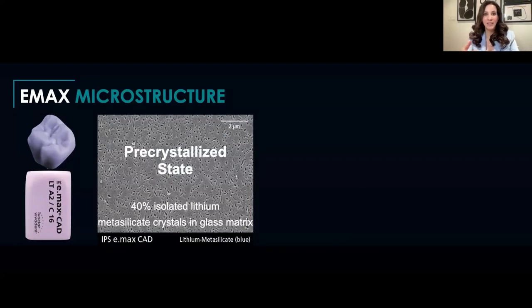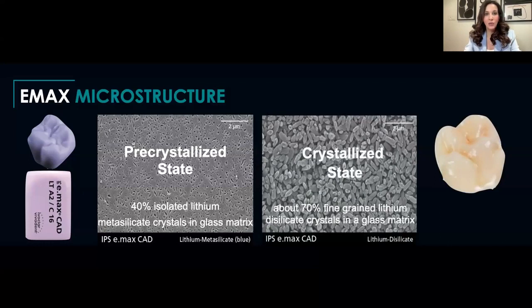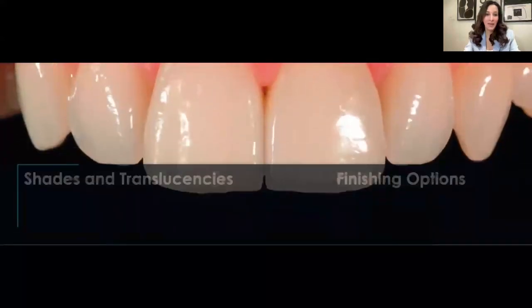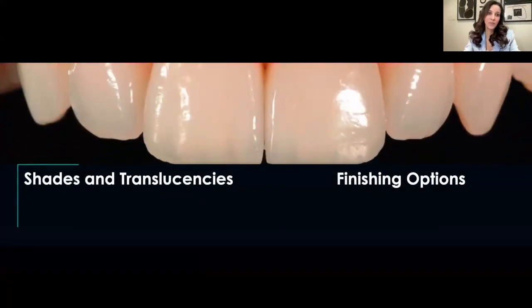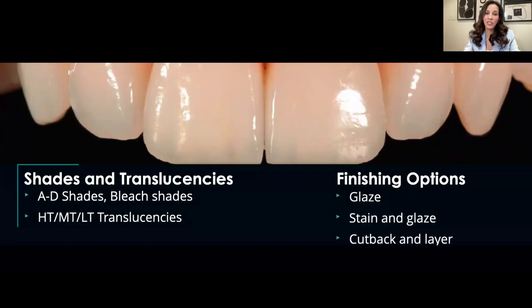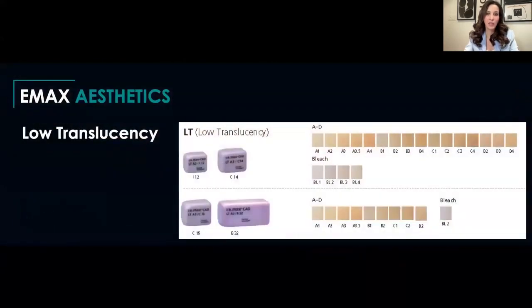So the material is actually milled in this pre-crystallized state. It's not strong at this state, but once it's crystallized, you have the infusion of the lithium disilicate crystals in this glassy matrix. So it's 70% fine-grained lithium disilicate in the glassy matrix. And you can see that Emax comes in a number of different shades and translucencies, including anywhere from the A to D shades. Bleach shades are available, and it's available in high, medium, and low translucencies. And your finishing options could be either just to glaze it, to stain and glaze, or to cut back and layer.